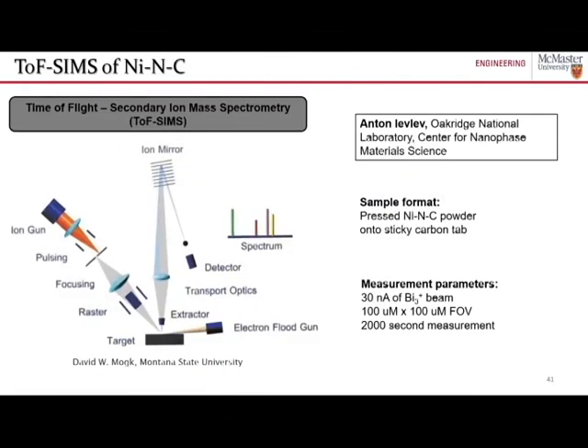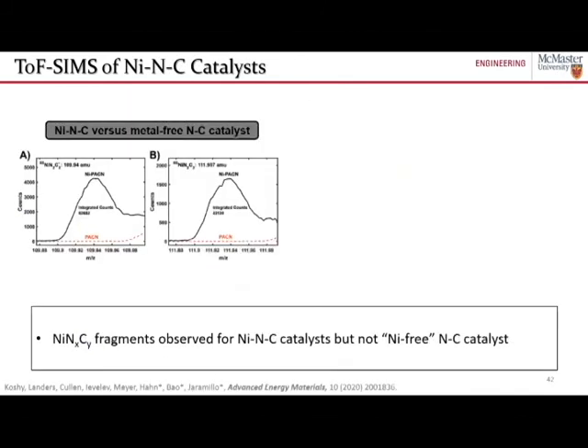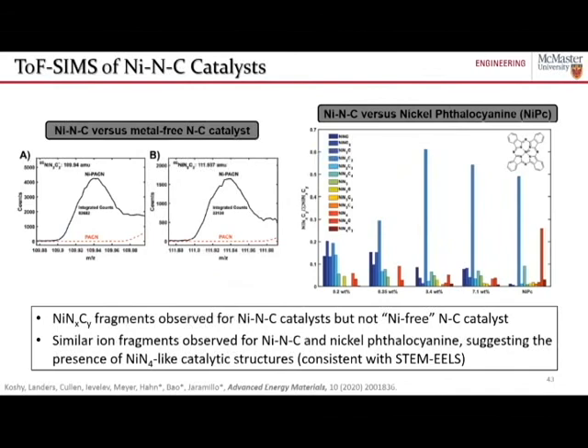He also did some ToF-SIMS analysis at Oak Ridge National Lab, and I'm not going to get too much into that, but the key thing to mention here is that nickel-nitrogen coordinated fragments were detected during the ToF-SIMS measurements, very similar to what was seen for nickel phthalocyanine. So again, providing another clue that it was nitrogen coordinated nickel single sites that were the active structures in these materials.